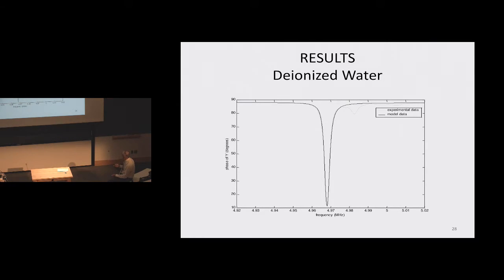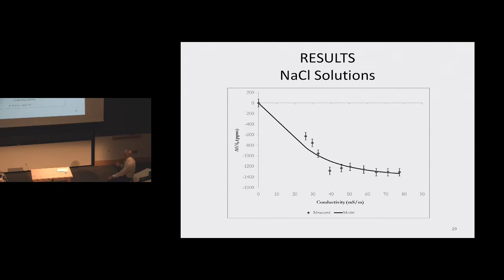What about the phase? The first one was a magnitude. This is the phase. And again, there is the corresponding frequency, the TSM frequency. Experimental data: a little bit of deviation over in this region here, a tiny bit over here, but otherwise a very good representation. All right, with that, what about the response of this sensor to the conductivity of sodium chloride solutions? Here we look at theory versus experimental results, whereas what I gave before was basically experimental results. This is the theory, the solid line model, and this is experimental data, which indicates that, although we're not exact, we've probably got a decent handle on what the equivalent circuit representation looks like.